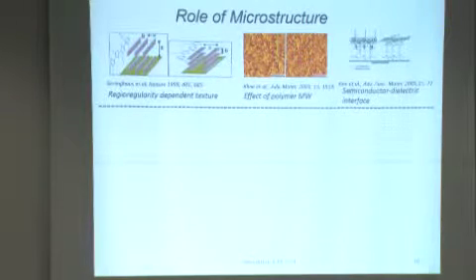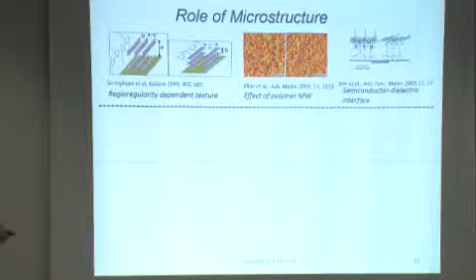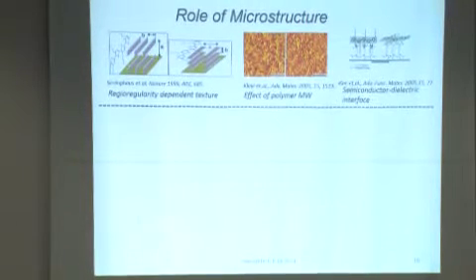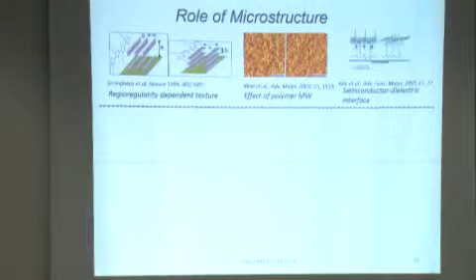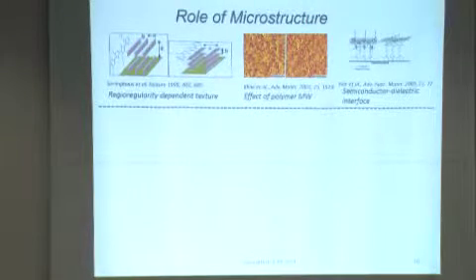This is a low molecular weight material of the same polymer. A very highly crystalline material in the solid state. In terms of performance, it's lousy. This is a higher molecular weight material, not as crystalline, a much more amorphous or multi-phase system in the thin film, but it has very high mobility. And then you can also do a lot of surface functionalization in order to control how the polymer orients itself on the substrate, and then depending on the orientation of the polymer, that can also define how charges move through that film.